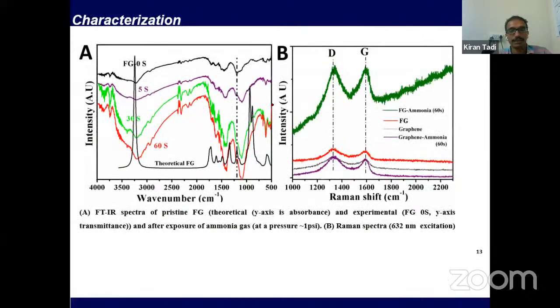If you see the characterizations of this molecule from the thermally reduced graphene, we exposed it to ammonia gas directly. This black color is without exposing, and 5 seconds and 30 seconds are the exposure levels we gradually increased here.